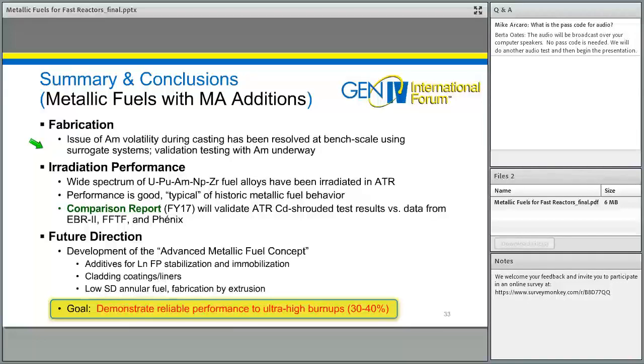Under irradiation performance, I showed really just a huge spectrum of fuel alloys that have been tested in our ATR test program, both with and without minor actinides. Performance tends to be consistently good and consistently typical of historic metal fuel behavior. So we're confident we can rely on what we've learned over decades and know that most of those behaviors will be borne out as we change the fuels as well.